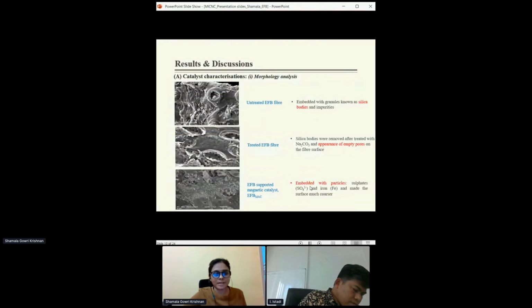For results and discussion, part A is the catalyst characterization. The first characterization is morphology analysis. The SEM image of untreated EFB fiber reveals that the fiber has silica bodies and impurities on the surface. While after the sodium carbonate treatment, the silica bodies were removed and empty pores appeared on the fiber surface. The treated fiber was further used for the impregnation process, where the particles were embedded on the fiber and the surface of the fiber became much rougher.